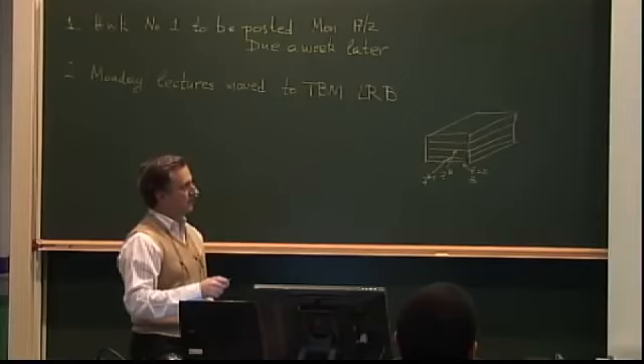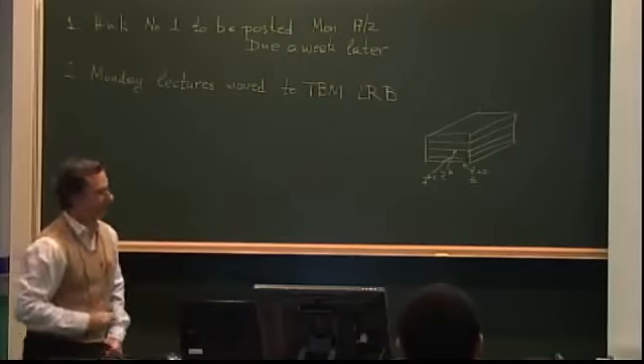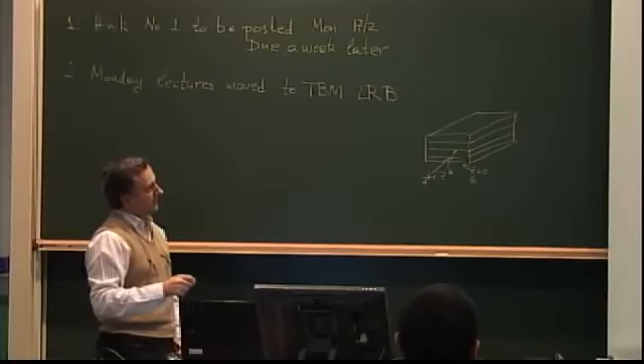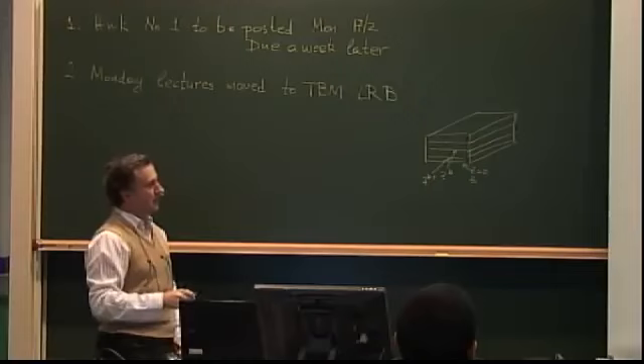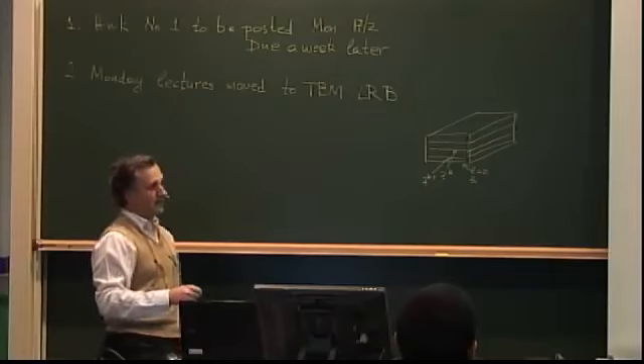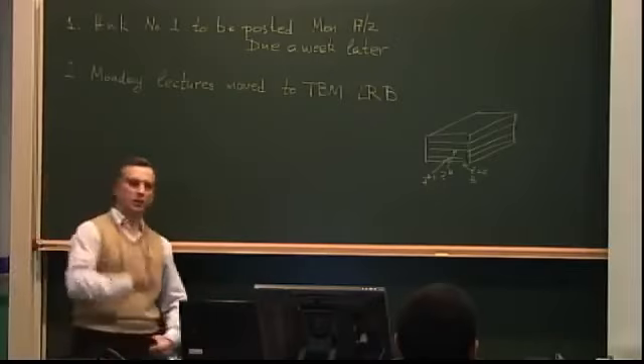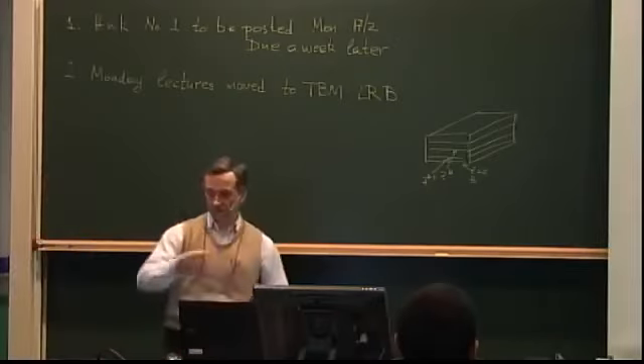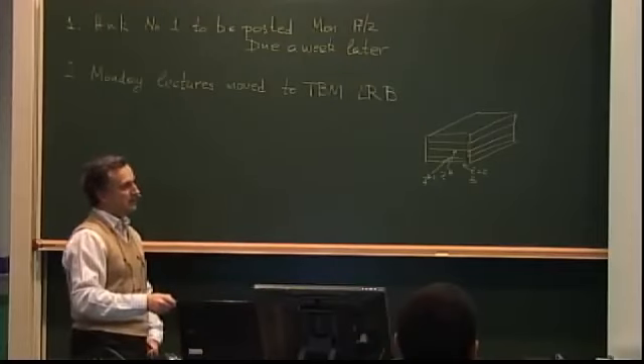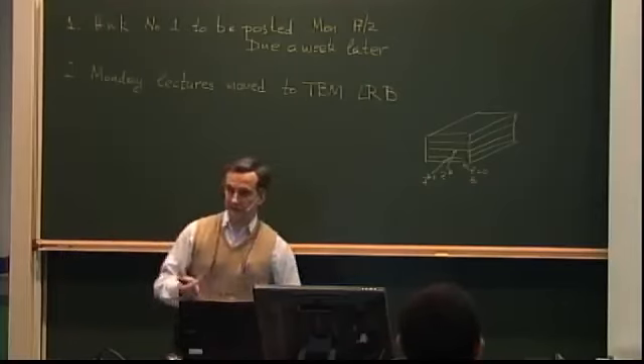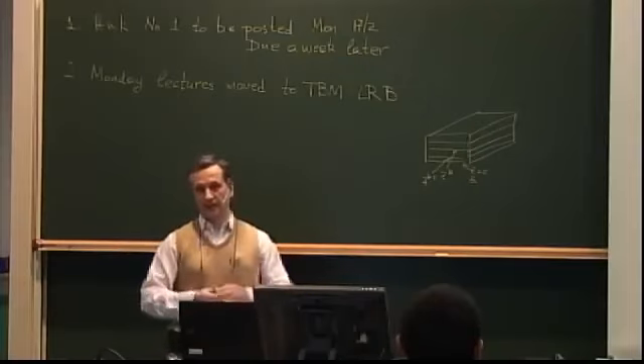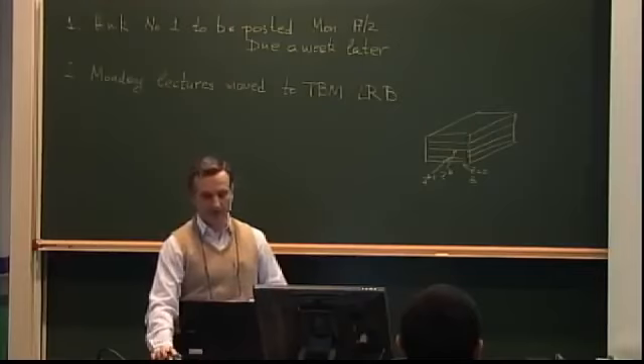So we take the basic relationship, integrate with respect to z, which means this integral of sigma x will become our Nx, the force in the x direction of the laminate. And then the Q11 integration will become the A11 we saw just a little while ago, the A12 and the A16, which are lumped here. And then the remaining are new quantities, which are now the Q's times the integral of z dz instead of Q times the integral of z squared dz or Q dz. So this new integral is now our B matrix, so that's where the B comes from. And we have, as a result, the coupling matrix that tells us by how much the structure would bend if we were applying an in-plane load, assuming it's a composite structure.